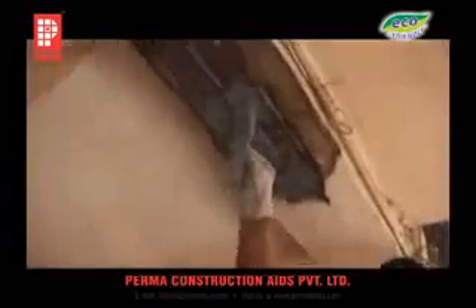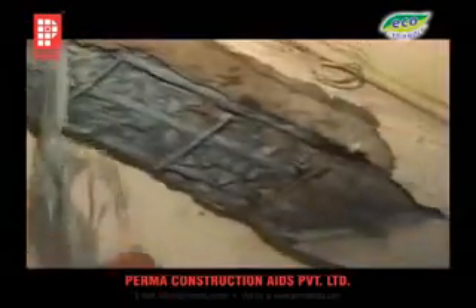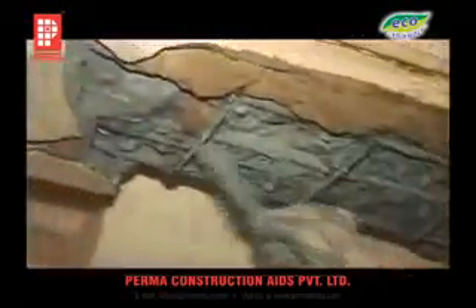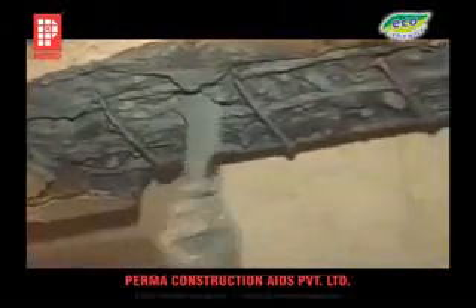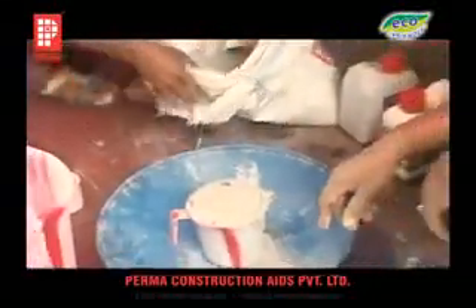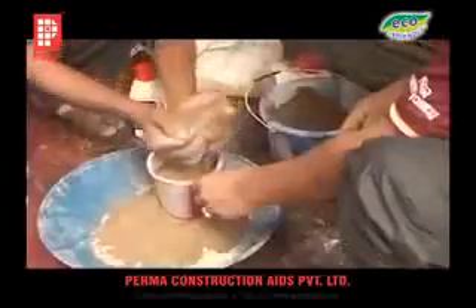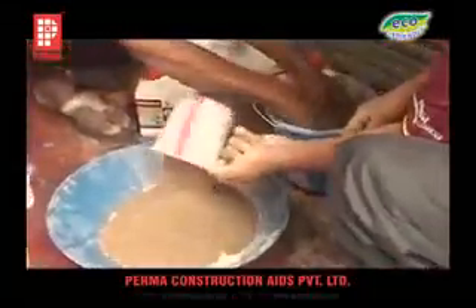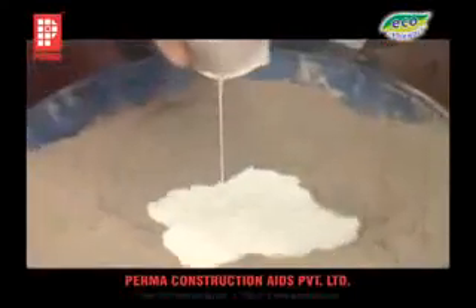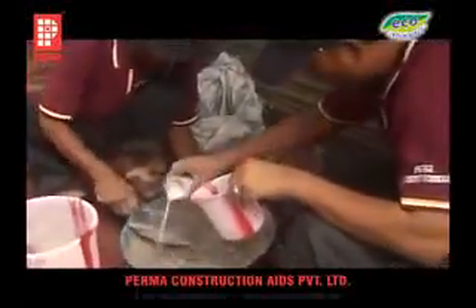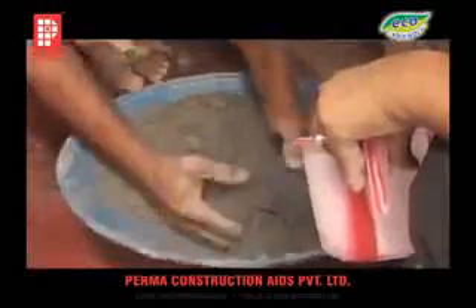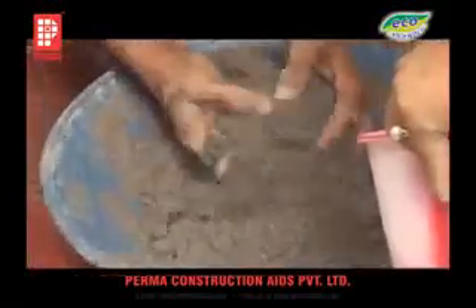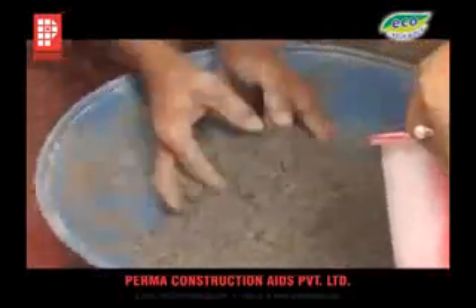After this passivator coating dries up, say after an hour or so, the concrete surface is made good with a mortar, prepared by mixing 1 kg of cement, 2.5 kg of Zone 2 sand, 200 ml of Permabond SBR and 150 ml of water. This mortar is applied on SBR and cement slurry applied all over the broken concrete and the reinforcement as a bond coat.